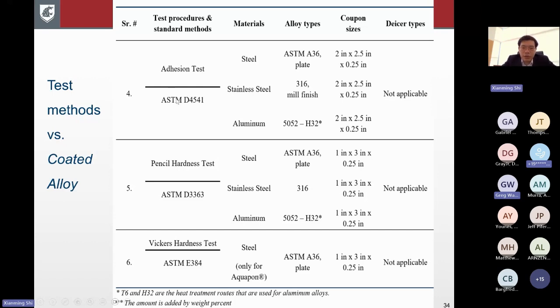And then as a coating on vehicles, sometimes it's really important to ensure the adhesion. So we also test the adhesion and test the hardness. For instance, if it's underbody coating, especially, the coated surface may experience some abrasion by abrasives or sand. So a hard surface will be preferable. So we tested hardness, and there are 2 tests. One is a pencil hardness test, but for the even harder coatings, we end up using the Vickers hardness test.